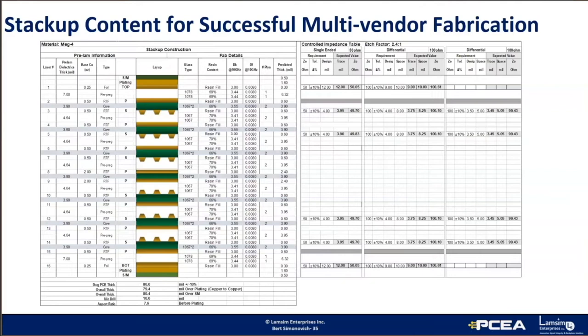Copper foil weights should be included and match the thicknesses as well. And for critical high-speed designs, you should include copper roughness to make sure it meets your loss budget. If not, there's no way for the fabricator to know what you really want and may choose a default foil, which is often rougher than expected.